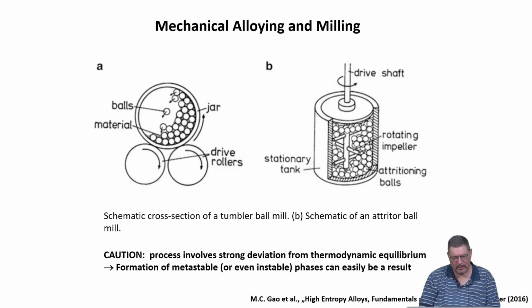But also you always have some material from your mill or from the balls inside of the mill abraded and mixing with your original material. So it means that you can never avoid some of the impurities from the materials the mill or the balls are made of going into your material. If you're fine with this, or if maybe the mill and everything is steel-based and you have also an iron-based alloy, then maybe it's not such a big deal. But if on the other hand you don't want to have iron in your material, maybe use a different ball mill. There are some based on tungsten carbide or so, and then you can avoid getting these mixing effects into your material.